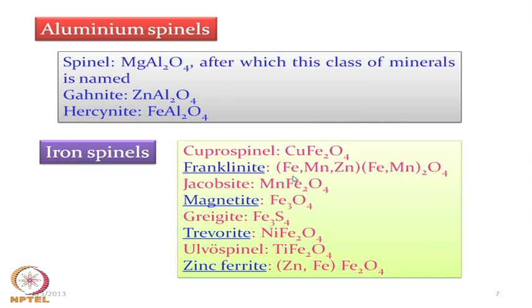The first example, a very useful one, is cuprospinel, where the A site is occupied by copper. Then franklinite, where the basic structure is formed not only by iron but also by manganese. Similarly, A sites can be substituted by iron, manganese and zinc, any of them, to give this particular structure. Then jacobsite is substituted by manganese for the A site. Then we have magnetite, which has iron on both sites. Then greigite, whose arrangement is based on sulfur, which is a different class, the thiospinel structure. Trevorite is based on nickel, and then there are titanium, zinc and iron ones. Like greigite, the oxide lattice has been changed from oxide to sulfide.